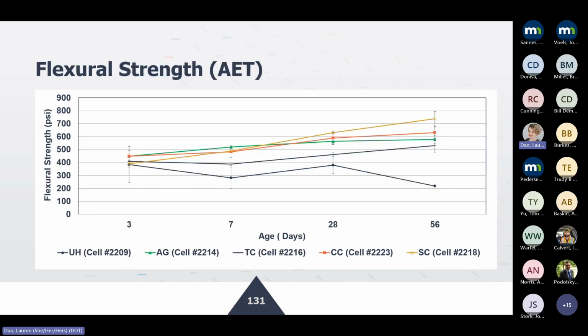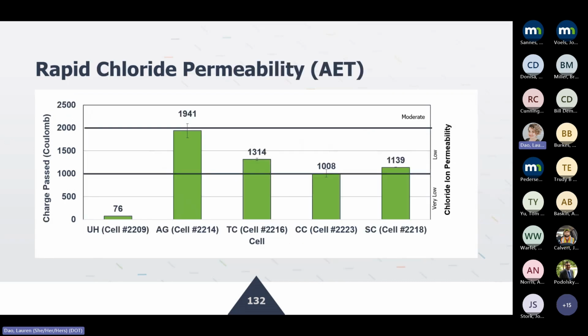And then when you look at the flex strength, one glaring observation you see is the ultra high, which has results going up and down. That's mainly because they could not really cast proper specimens there. So I would take the results for ultra high with a grain of salt, because the mixture that was received was very stiff, they could not make proper specimens.